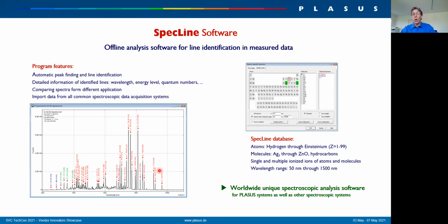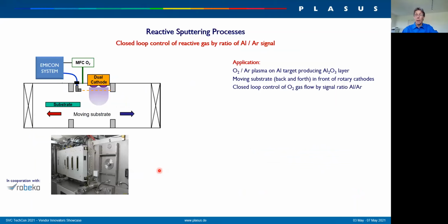And now, making use of all these tools I have shortly introduced here, I want to show you some examples of what you can do with it. I want to start with the reactive sputtering process. Here we wanted to make an aluminum oxide coating by a reactive process with an aluminum target on this dual cathode, and we wanted to control the oxygen flow. The challenge was that the substrate was moving back and forth, and thus we have not really stable plasma conditions, and we needed to make the control stable nevertheless.